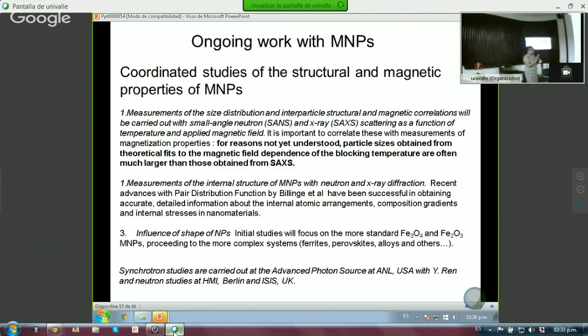So, to go back to the small angle measurements, you can do them by neutrons or X-rays, and each of these techniques will highlight different elements. For example, with X-rays you're going to see the heaviest element. So in the case of iron oxide, you will see more of the iron than the oxygen. And if you do it with neutrons, it could be the reverse. So you highlight different elements. And you can also check the blocking temperatures.